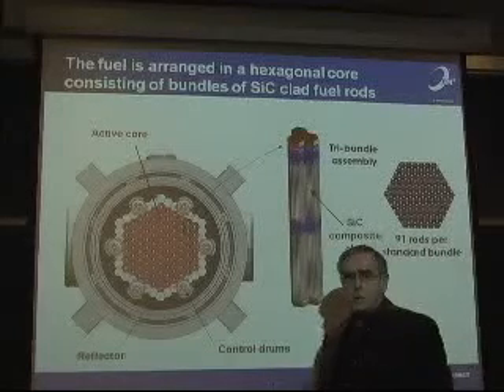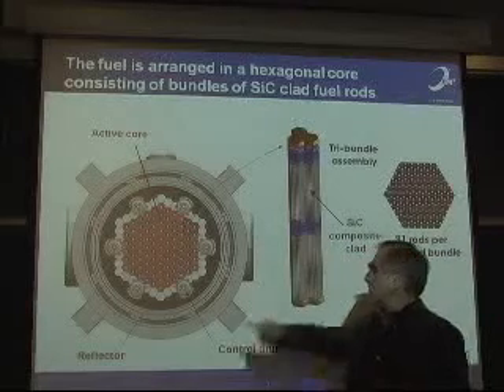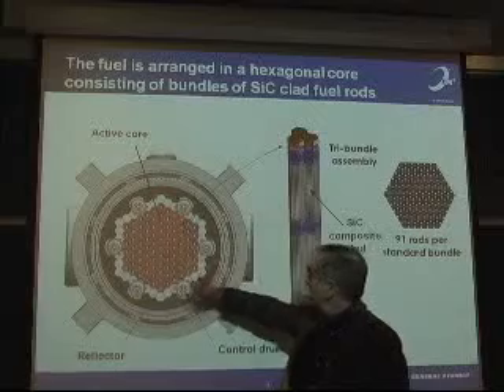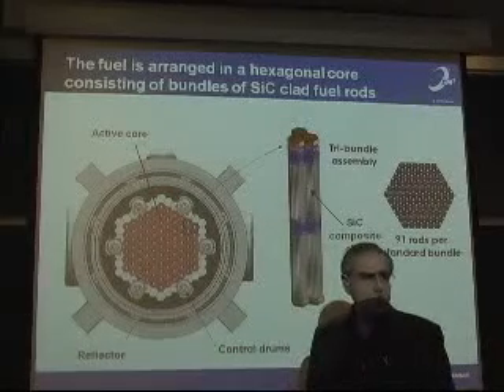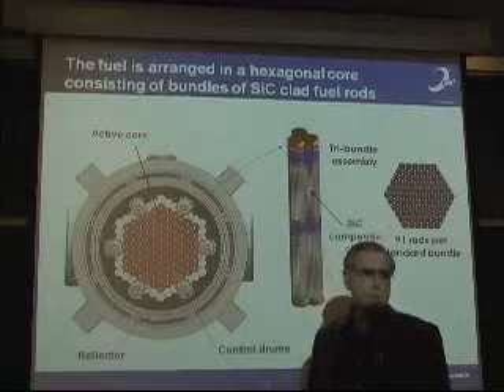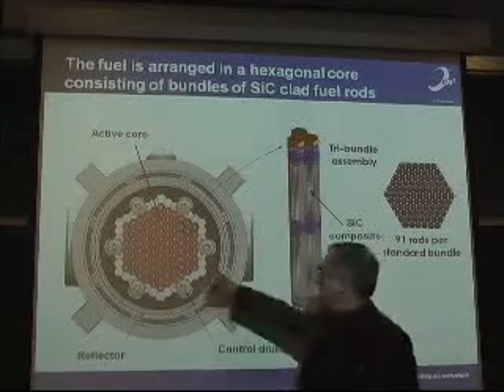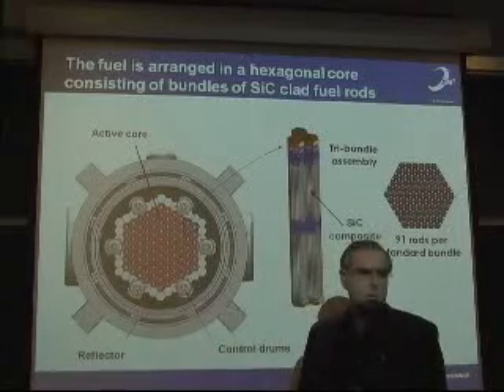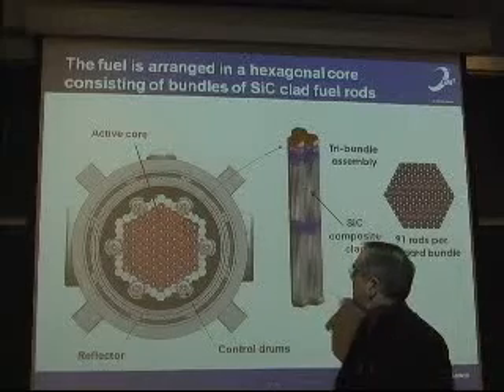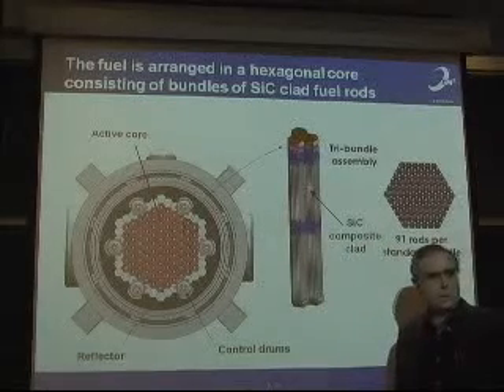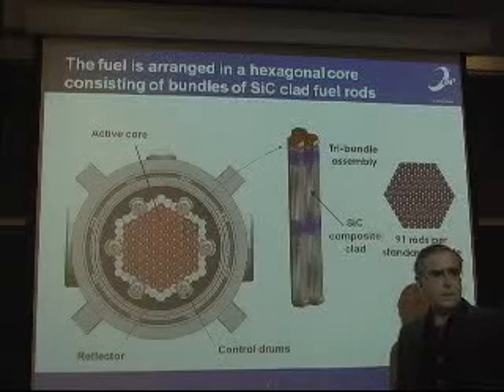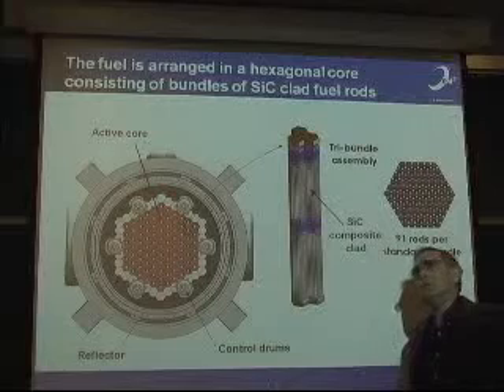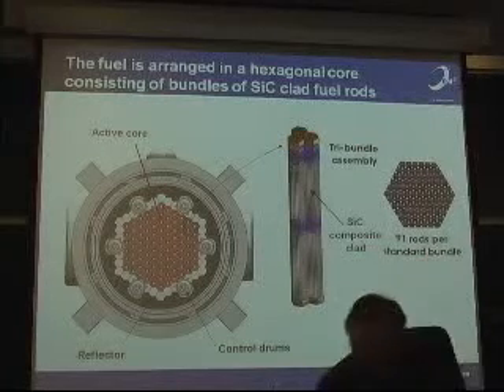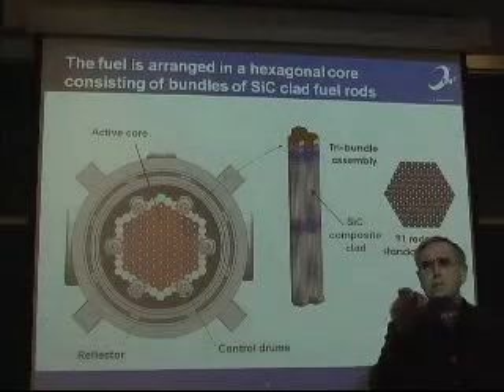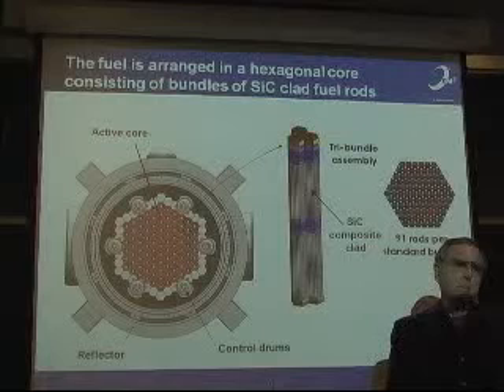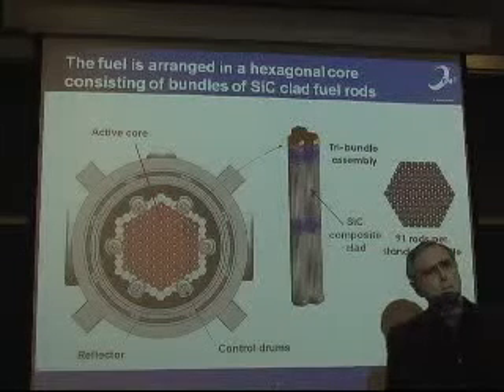In order to make this work, we have to have really low leakage in this core. So this inner reflector is beryllium carbide. And it has an average of about 25 centimeters delta R, and then the cheaper graphite outer reflector. What's that purple thing in the middle of your diagram? Oh, that's just a grid, a spacer grid for holding the rods. So the minimum space between rods is not quite 3 millimeters.